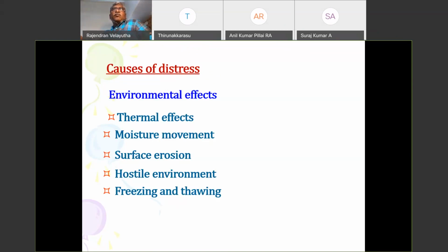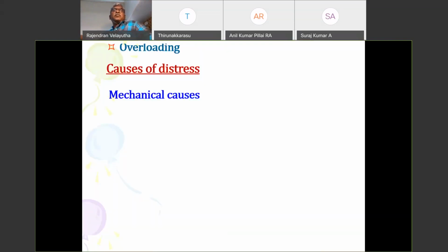Before the pre-monsoon, like now, till April, May, the ambient temperature is about 30, 40, 45 degrees, and the concrete temperature is anywhere around 47 to 48 degrees. And all of a sudden, in the afternoon, maybe around 3 o'clock, you have a shower that falls onto the concrete, in an area like a podium slab, and the temperature of the slab comes down suddenly, where we get a lot of cracks. We encountered a number of such cases in the recent past.